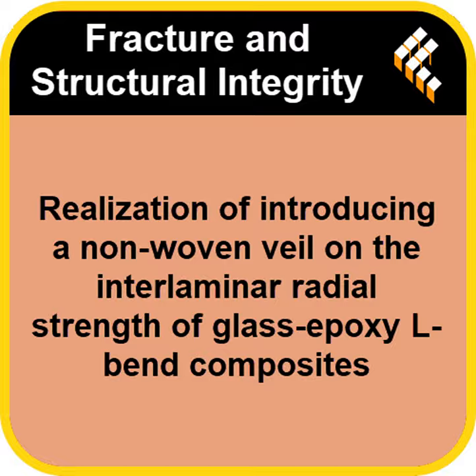Not significant, meaning the improvement could have just been random chance. Pretty much. The p-values were relatively high, 0.14 and 0.07. So, while the overall strength went up a bit, the glass veils weren't reliably tackling that core delamination stress nearly as effectively as the low-density carbon veil did.